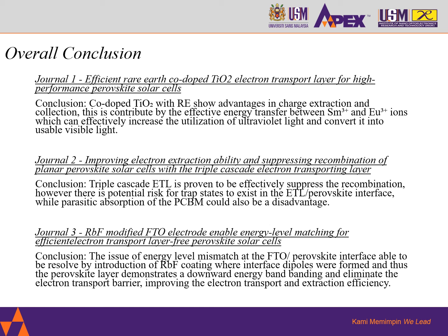From journal 2, we learned that the triple cascade ETL is very effective in suppressing recombination. However, from the IPCE, we also learned that there is a potential parasitic absorption phenomenon caused by the PCBM. So this will eventually be a disadvantage when it comes to mass production.